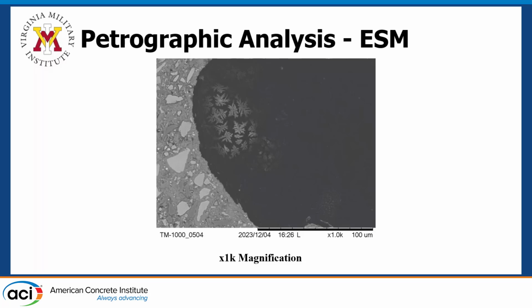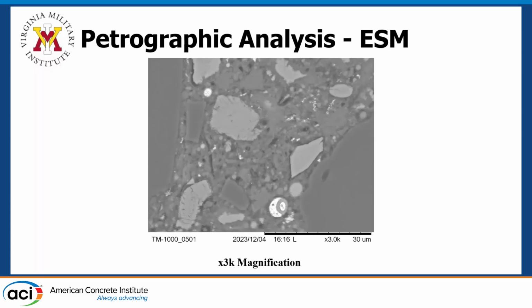So this is on the edge of a void, and those flower-like structures there in the center are due to the epoxy resin of each standard thin section. And this is where I'm really interested. So the 3K magnification. If you see that piece of aggregate over there to my left, y'all's right, it has a thin black line around it. That's the interfacial transition zone.